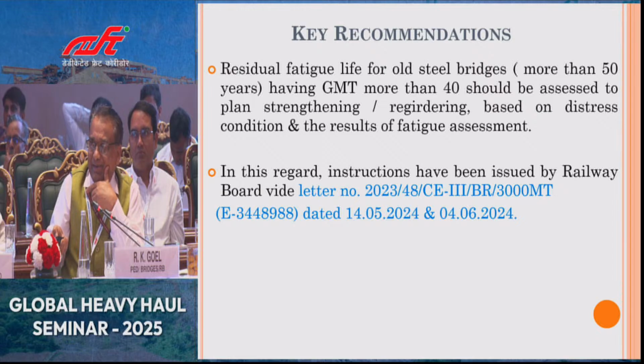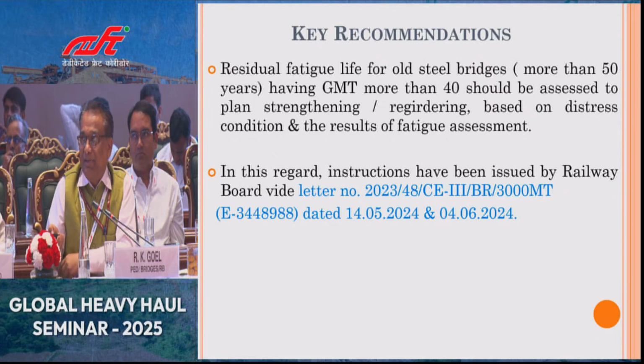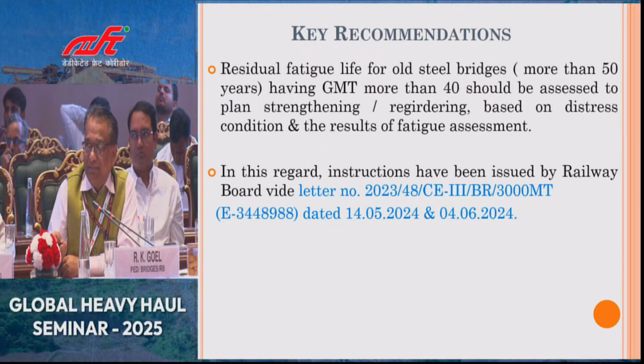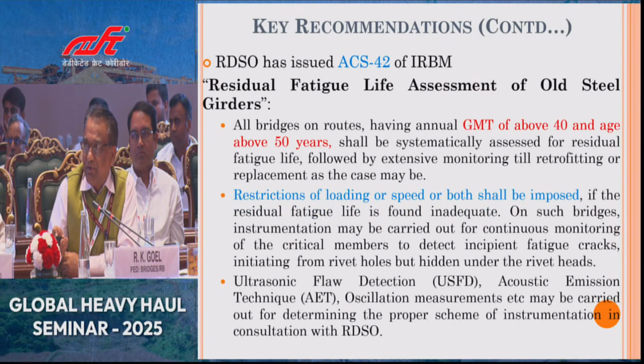So the recommendations are that the residual fatigue life for old steel bridges, which are more than 50 years, having GMT more than 40, should be assessed to plan strengthening, regirdering based on the distress condition and the results of fatigue assessment. So we have already issued the instruction in this regard from Railway Board in the month of May and June 2024. And then some correction slips have been issued in the bridge manual for periodical assessment of old steel girder bridges, which are having GMT more than 40 and age above 50 years.